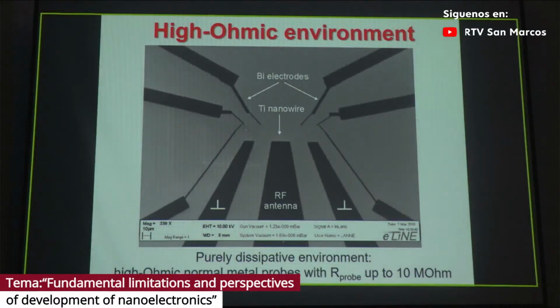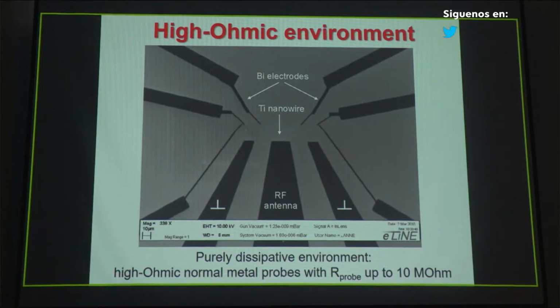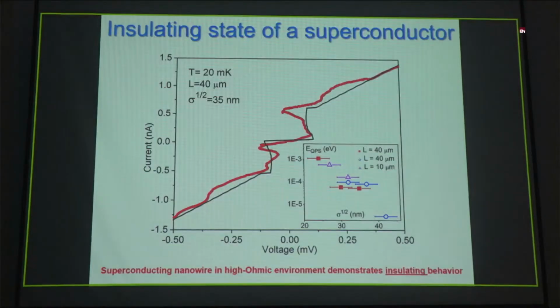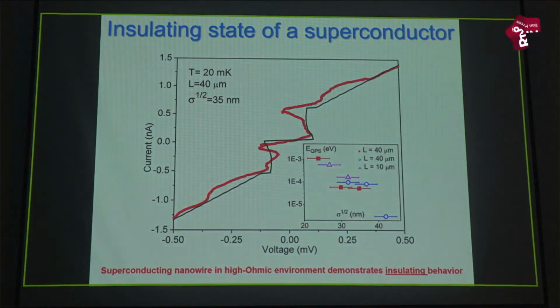So that is the structure which was fabricated by us. The device itself is a very tiny nanowire with a cross-section of about 25 nanometers, and it was connected to the external world by very high ohmic bismuth electrodes. Each of the electrodes was about 10 megaohm resistance. And the RF antenna was used just to pump in high frequencies, a few slides later I will show why, or to use like a gate to change the mobility of the device. So the IV characteristic looks like this.